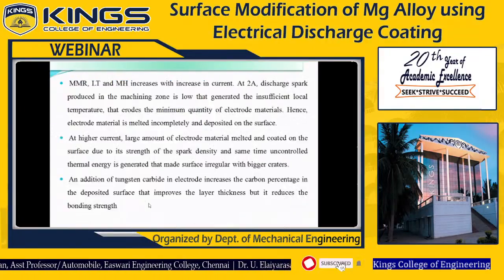Here, some of the mechanism is also given. The MMR, LT and MH increase with increase in current. At 2 amps, the discharge spark produced in the machining zone is very low. That produces insufficient local temperature between the electrode and workpiece, which erodes only a minimum quantity of material from the electrode and deposits it over the surface. At a higher current, a large amount of electrode material is melted from the electrode and deposited over the surface, and this also develops uncontrolled metal transfer.